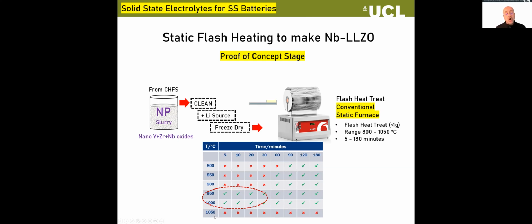But as you go to too hot, and this is where the Goldilocks bit comes in, I suppose, at 1050, we're not seeing a complete reaction. And what's actually happening is lithium loss, the lithium precursor is volatile. And at higher temperatures, lithium loss from evaporation of the lithium precursor becomes competitive. And it actually means the reaction can't complete because you've lost too much lithium during the time that it's in there.